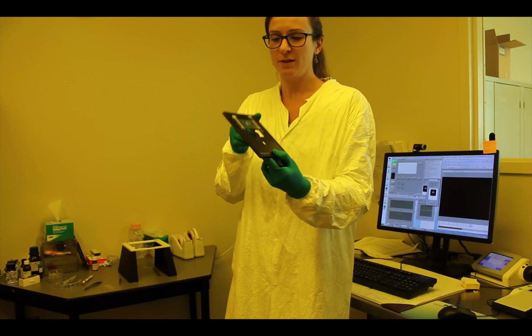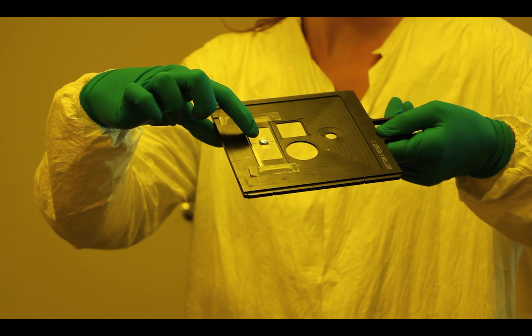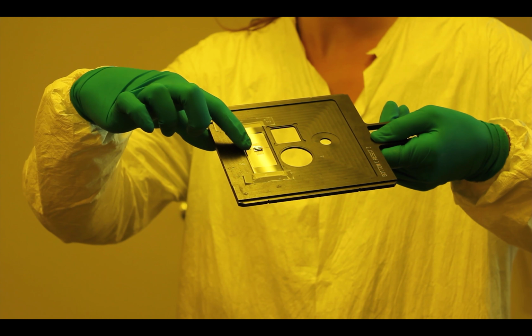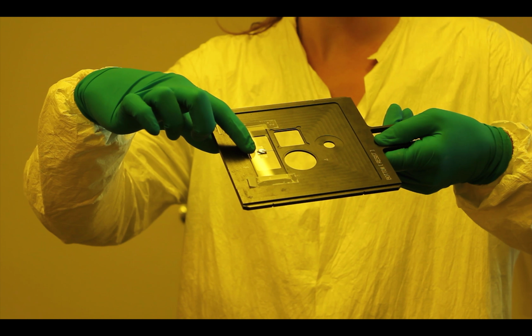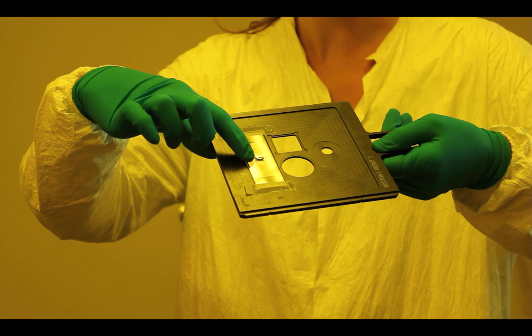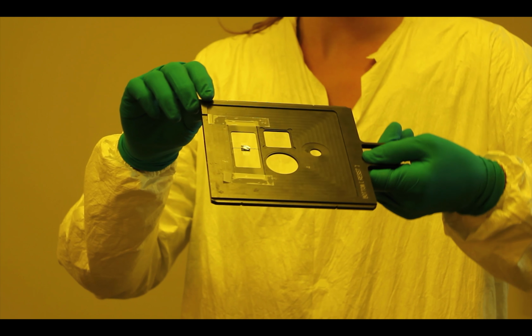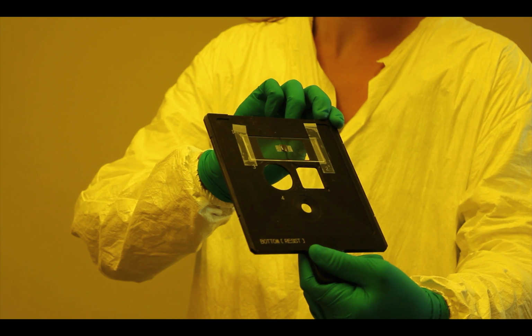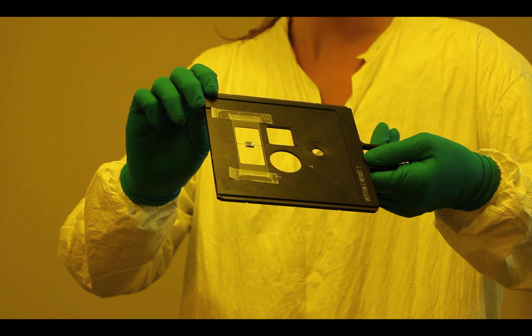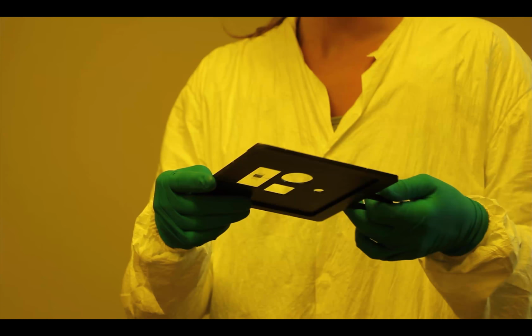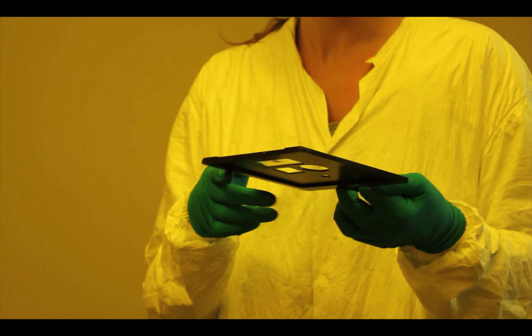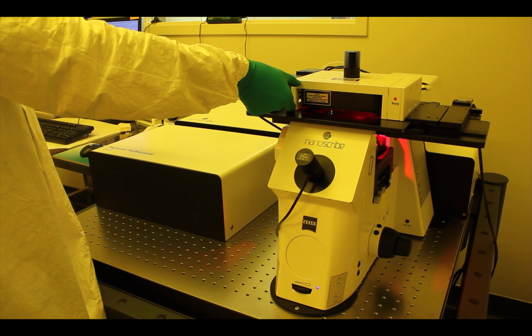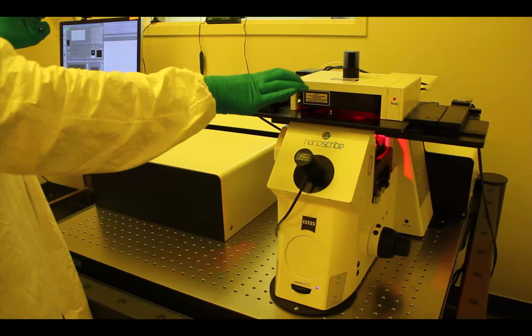So here's our sample holder. Right here we have a piece of double-sided tape with a tiny piece of silicon on top of that, and then there's a droplet of photoresist, which you can kind of see. It looks like honey. It's a very viscous, light-sensitive material, and so that's what we're going to be making our structures out of. Piezo stage, which is a really high-precision stage that can move your sample around.